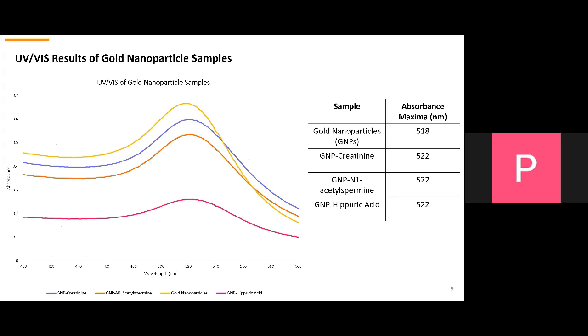We characterize gold nanoparticles using ultraviolet visible spectroscopy. This is because gold nanoparticles exhibit a phenomenon called surface plasmon resonance. This is where they absorb light in the green-blue portion of the visible spectrum and reflect red light, which gives them that dark red wine color. As you can see here, gold nanoparticles prior to any conjugation reactions exhibit an absorbance maximum of 518 nanometers, and this steadily increases after binding the linker and the metabolite. This has been correlated with an increase in particle size, which is an indicator to us that the linker and the metabolite have been bound.